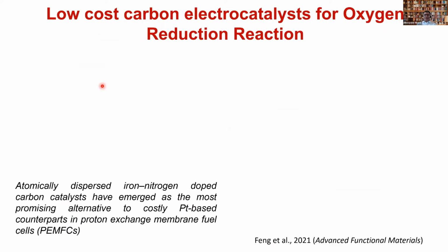So in this paradigm, there's actually something else that was very cool that we were able to do. We were fortunate to be invited to help a group at Imperial College London, who was trying to develop low-cost carbon electrocatalysts for the oxygen reduction reaction. And this is an area that has been very prominent recently, because it has been found that dispersed iron nitrogen doped carbon catalysts have emerged as a promising alternative to costly platinum-based counterparts in fuel cells.